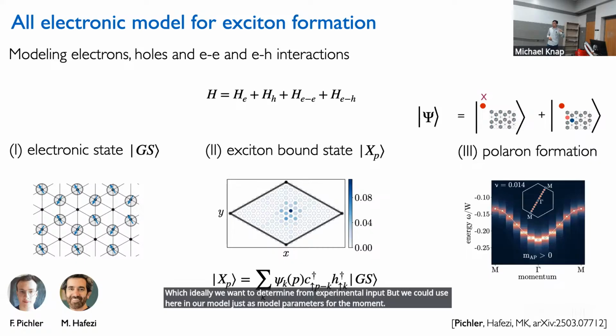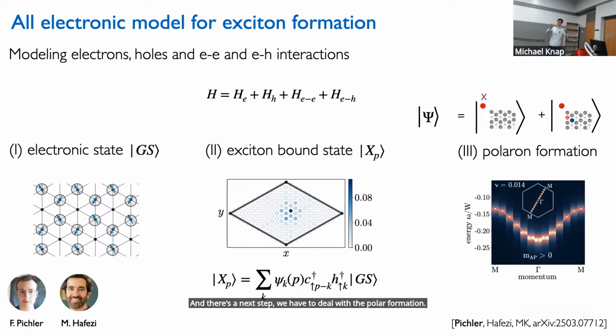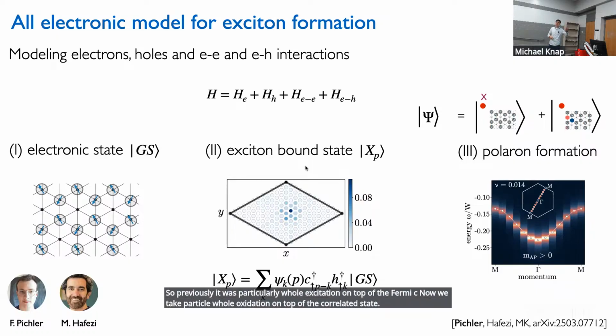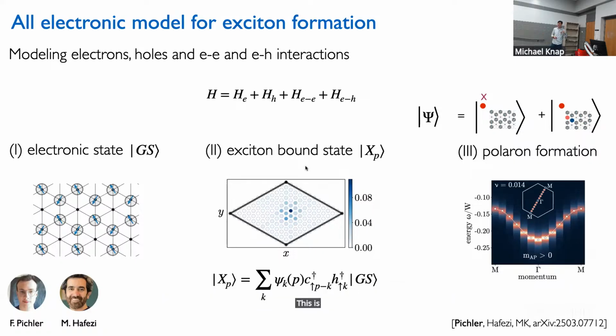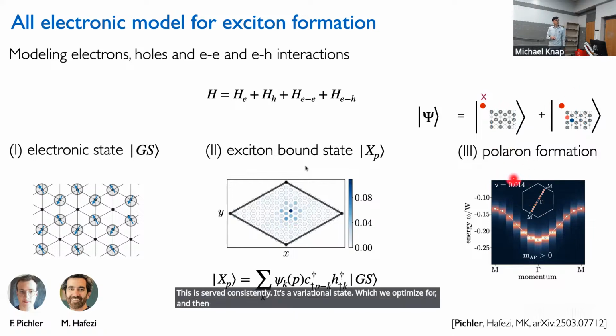And as a next step, we have to deal with the polaron formation. So far, I have the correlated state and exciton formation on top of it. Now I want to trace the exciton with the charge environment. How do we do it? It's literally the same as we did before: we take the exciton and correlated state, plus a superposition of exciton and particle-hole excitation in the correlated state. Previously it was a particle-hole excitation on top of the Fermi sea. Now we take a particle-hole excitation on top of the correlated state. This is solved self-consistently. It's a variational state which we optimize, and then we can extract out of this the spectrum of the polaron. So here is the energy of the resonance as a function of momentum.